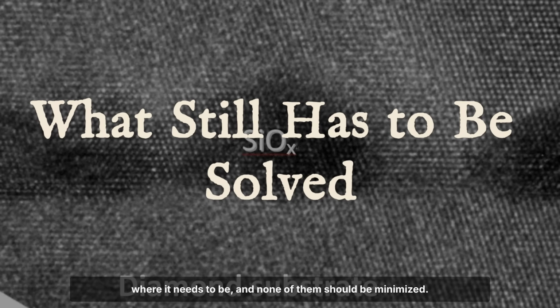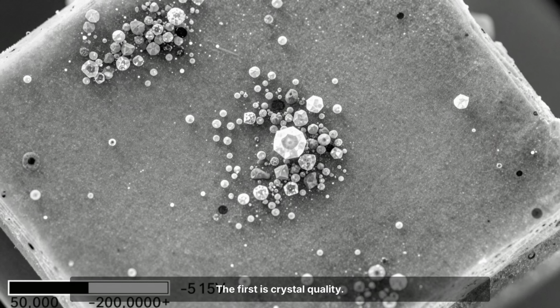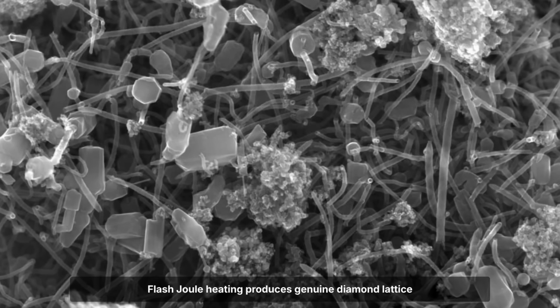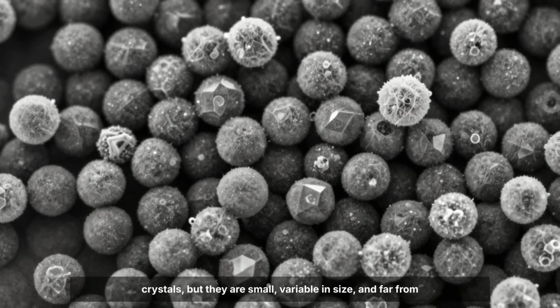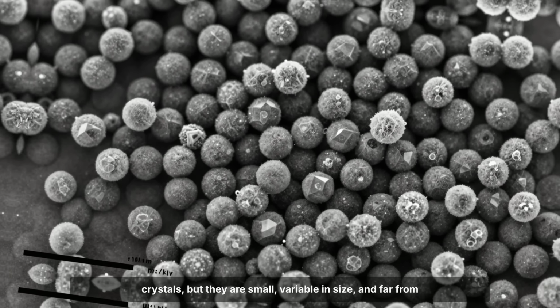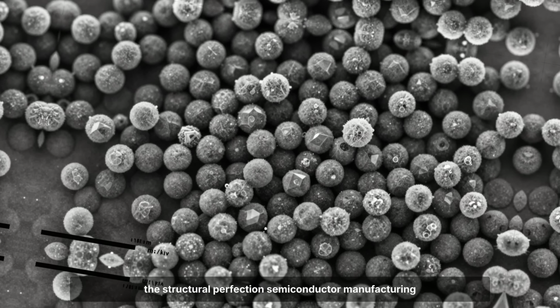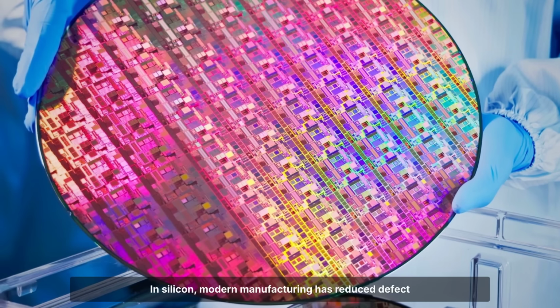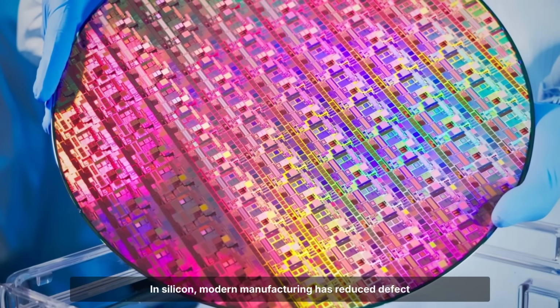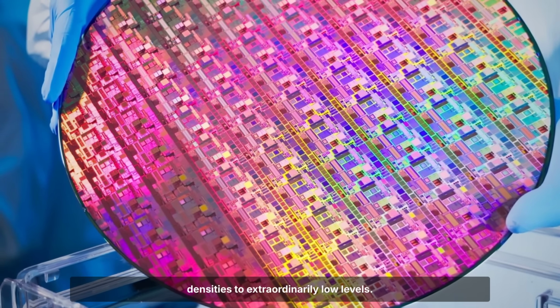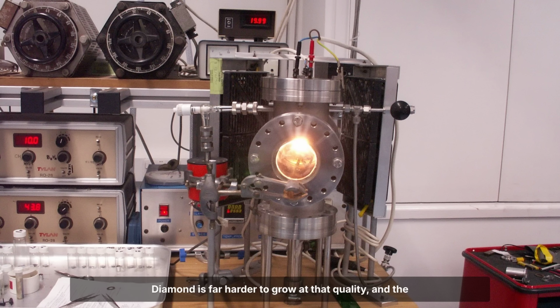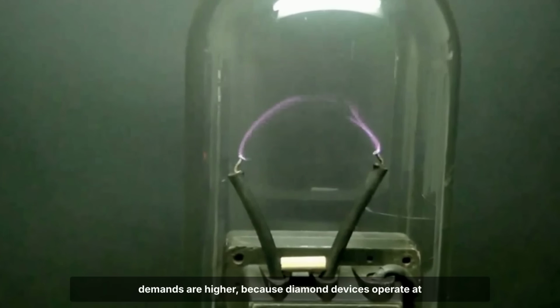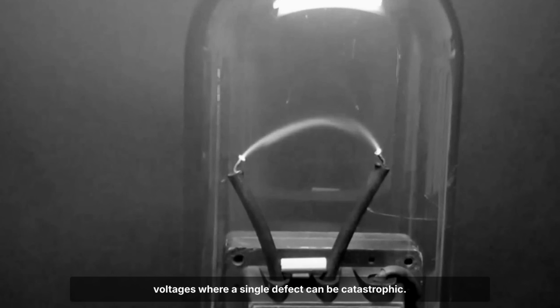Three real obstacles stand between where this is now and where it needs to be, and none of them should be minimized. The first is crystal quality. Flash Joule heating produces genuine diamond lattice crystals, but they are small, variable in size, and far from the structural perfection semiconductor manufacturing requires. In silicon, modern manufacturing has reduced defect densities to extraordinarily low levels. Diamond is far harder to grow at that quality, and the demands are higher because diamond devices operate at voltages where a single defect can be catastrophic.